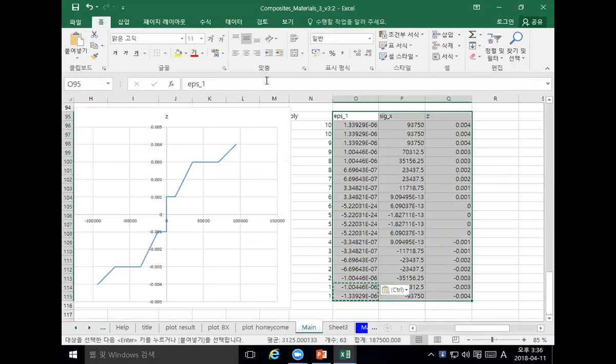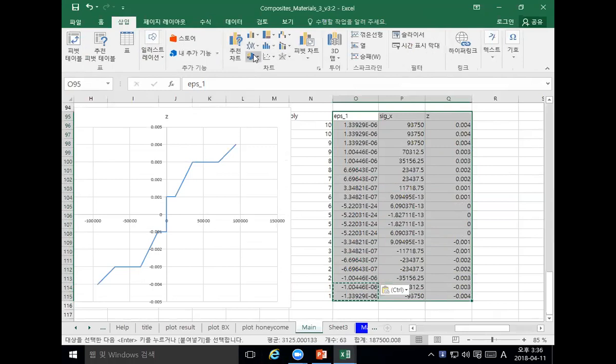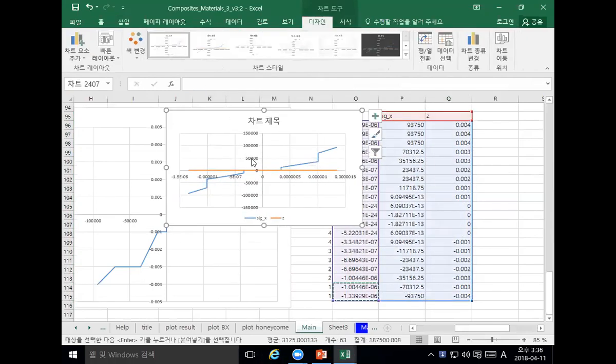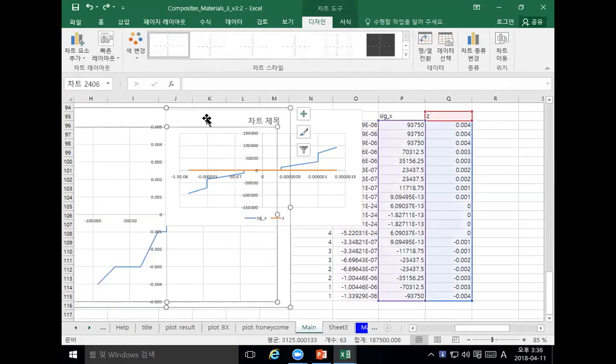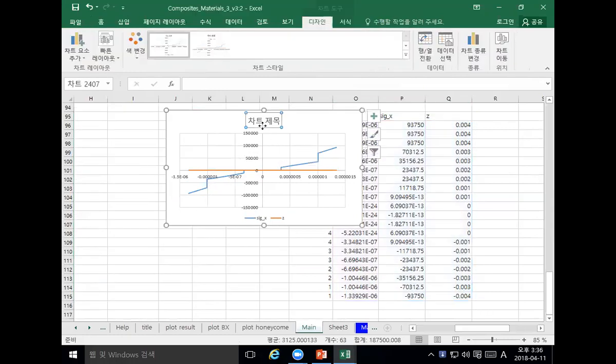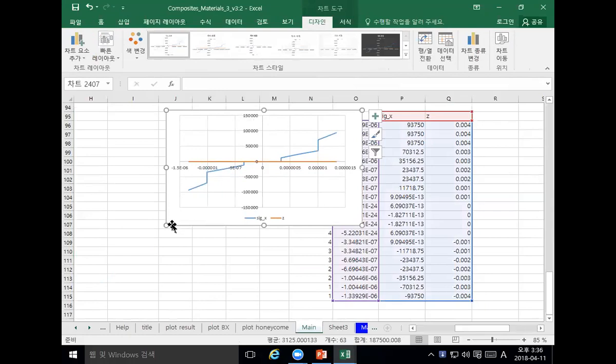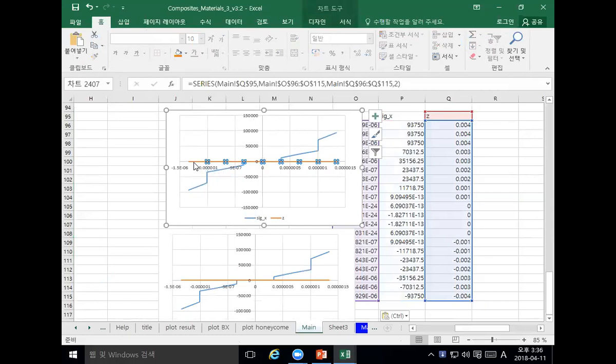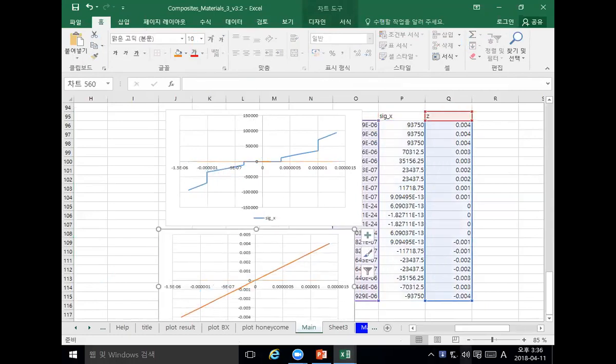So we just copy and paste. And as you can see, if we plot them, let's see what will happen. Okay. So as you can see, this is the strain. When I bend, the strain inside is always straight, linear, regardless of angle. That is the one we really need to remember. Why? When it's between, it cannot slide, right? Each ply, they are attached together. So when it bends, they always have to move together. So the interface is always a smooth curve, smooth strain.